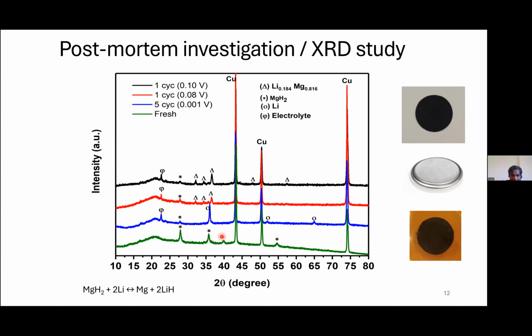What we have observed, what is the test result? The green one is the fresh sample, and different conditions we have tested, and what we identified is that at the intermediate stage, there is an alloy phase, a lithium magnesium alloy phase, that refuses to convert again to the end material. We are stuck with that, and we need to identify strategies to break this alloy and convert again to the end material. A partial conversion is there, but not full conversion. But in the literature, people are suggesting promising ideas, and we are trying our own approaches. This way, slowly, we are getting into reversibility, as much reversibility as possible. And this line of research is also very, very promising.